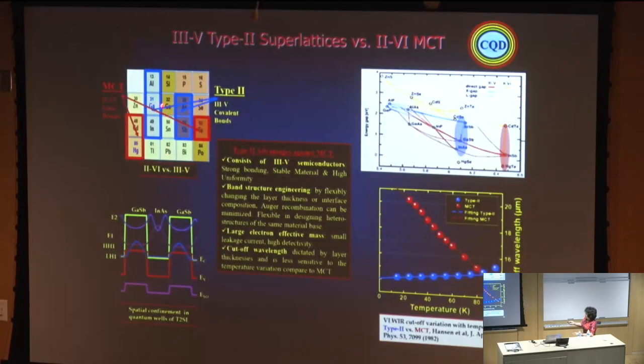All of you know that here I explain column 3, column 5, 3-5, column 2, column 6, 2-6. The 2-6 are ionic. Here I have the energy gap as a function of lattice parameter for cadmium telluride, mercury telluride, and mercury cadmium telluride. As you can see, these binaries are lattice matched with each other, perfect lattice match, but there is no substrate here. And at the same time, we can make the focal plane array detector with different wavelengths. But for each wavelength, you need only one composition.